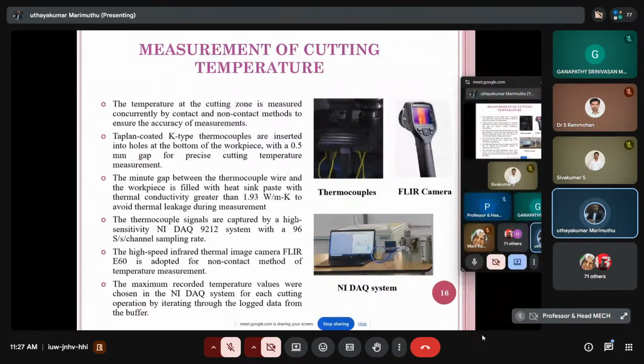This is the measurement of cutting temperature. So how to measure the temperature? There are two types: one is the contact type, the other is the non-contact type. Both methods we have adopted. A K-type thermocouple was used for contact type measurement, and for non-contact type we used the FLIR camera. The maximum recorded temperature values were chosen in the NI DAQ system, and are reported for the study.